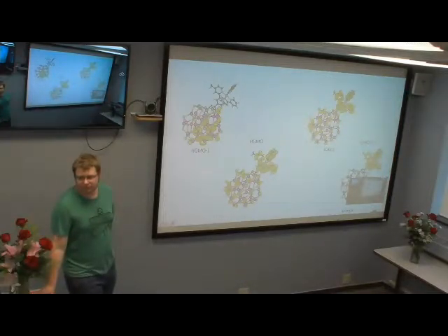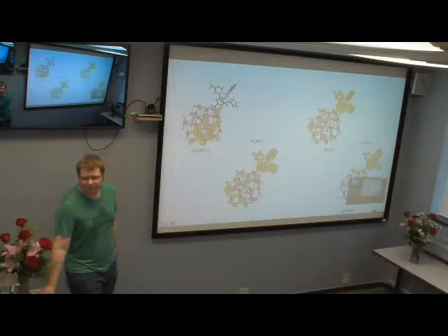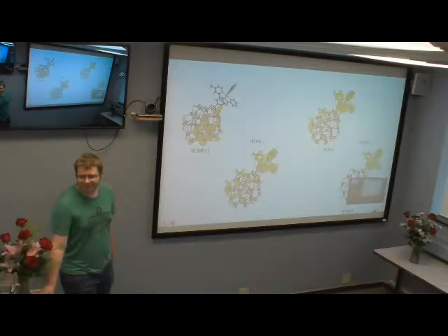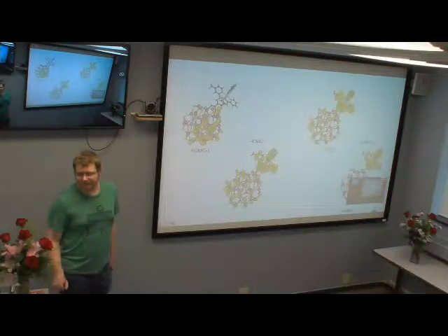And of course, you're in a classical regime for the quantum dot because they have much smaller vibrational frequencies for the inorganic materials. And again, this might be the reason why you heat it and why you really see this molecule making this motion, because these are really huge temperatures where these vibrations make an impact.